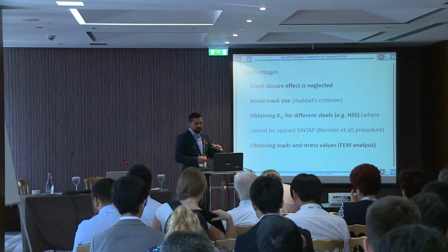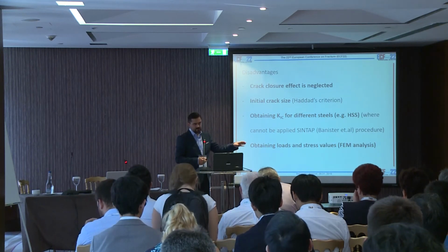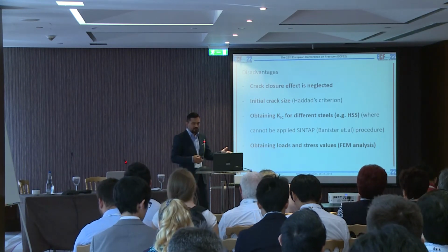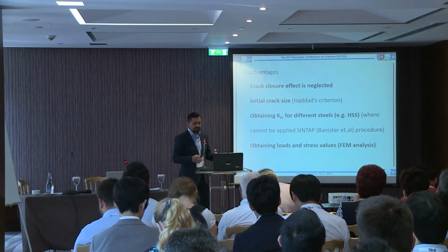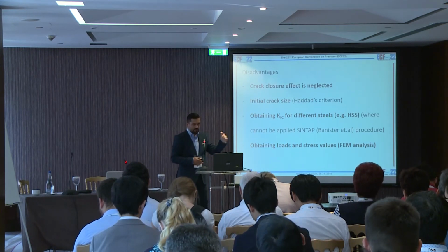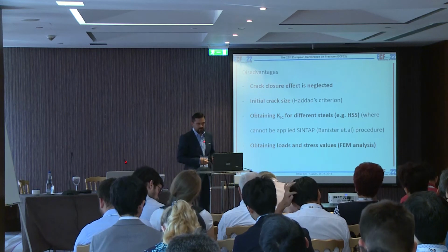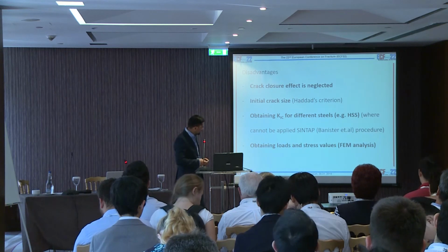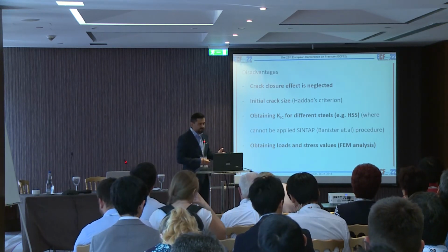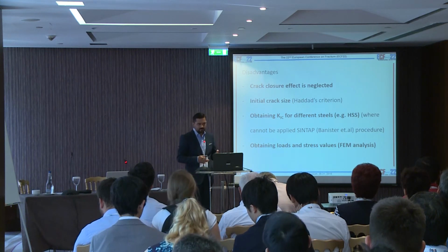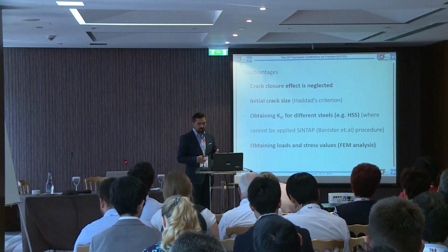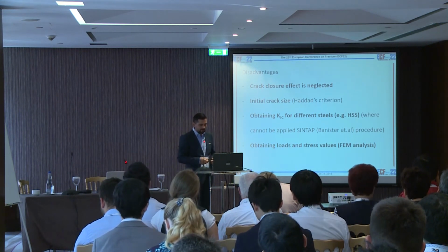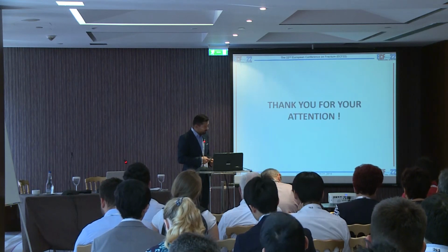Obtaining K1C will be difficult if high-strength steels are used. If you use S235 or S355, it's okay. But if you go higher, you have a problem applying the British standard procedure. Another downside is that obtaining the loads and the stress values implies a very large amount of work. It will need very hard work in this matter.